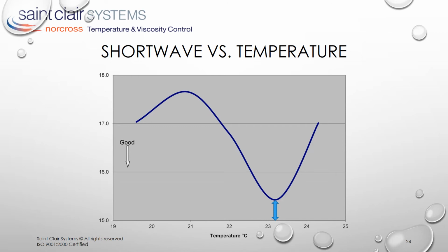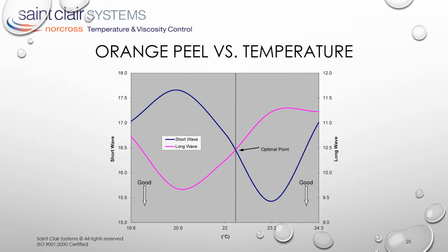This is virtually an inversion of the long wave graph. Note that these two plots cover the same 19 to 25 degrees C temperature range and also three steps of wave scan range. If we take these two data sets and plot them on the same graph, we can see the interaction, which represents orange peel versus temperature. This shows the balance point to optimize both long wave and short wave parameters occurring at about 22.3 degrees C.